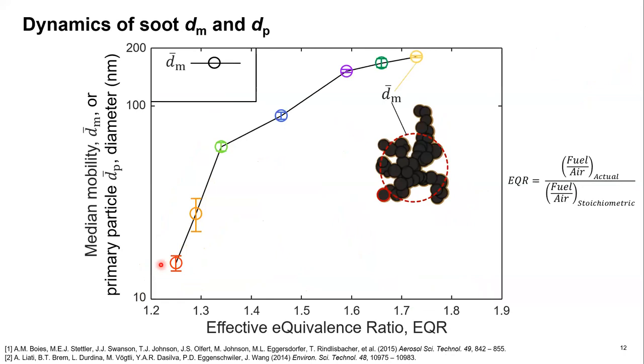As we saw on the last slide, the median mobility diameter increases with the effective equivalence ratio at first quite quickly, and then it levels off at the higher equivalence ratios. We also measured the primary particle diameter with transmission electron microscopy. And what we see here is that at the small equivalence ratios from 1.29 up to 1.59, we have a rather constant primary particle diameter of about 14 nanometers. After this point, it begins to increase slightly in the very rich flames up to 23 nanometers.